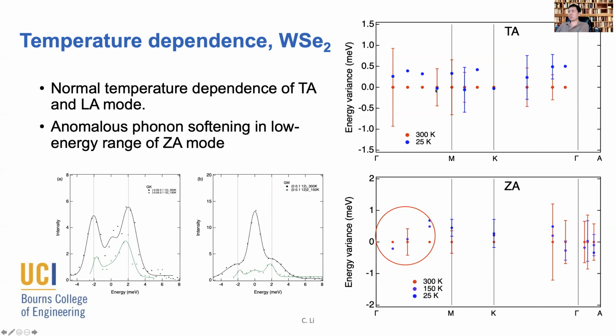On the other hand, the phonons are kind of broad, but the trend is pretty clear. And if you look at the ZA mode, on the other hand, we see an anomalous effect at low Qs, for Q points near the gamma point, near the center of the Brillouin zone. And the data quality is actually quite good, as you can see on the left-hand side, and the fits over those peaks, on both the energy gain and energy loss sides, are pretty accurate.